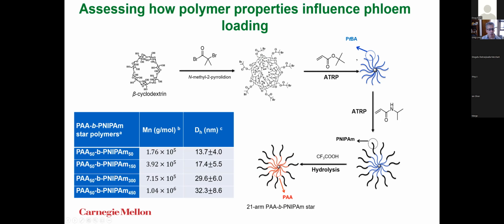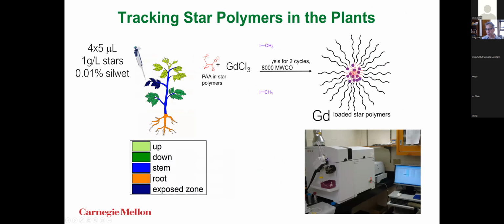And these star polymers, we made them different sizes. You can see their hydrodynamic diameters range from about 13 nanometers to 30-some odd nanometers. So we're looking at size. We can also look at charge. As I said, we load this PAA core with gadolinium, and it stays inside there. It's strongly bound. We've shown that it doesn't come out. So what we do is we put these gadolinium-loaded materials on the leaf, and then we go look for gadolinium in the rest of the plant, and it has to be our star polymers. We can figure out where they go. And you use simple ICP-MS to do that.